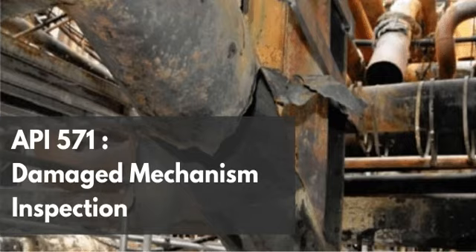When a technician applies a grinder to the crack location, they are physically excavating the crack tip. They are removing the anodic crevice where the localized dissolution is actually occurring. Oh, I see. Because this is not a mechanically driven fatigue crack, removing the sharp tip and taking it out of the immediate chemical microenvironment instantly arrests the mechanism.